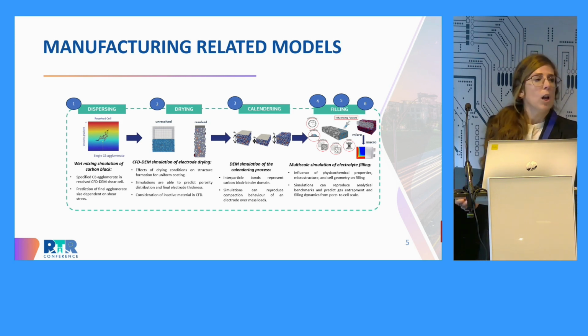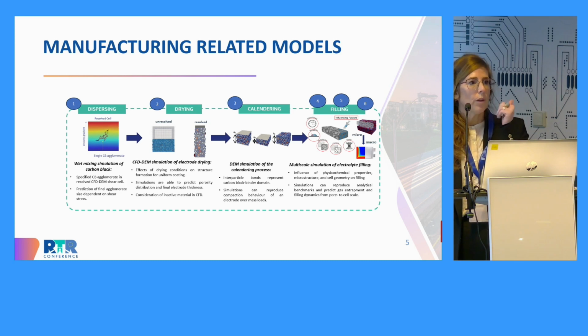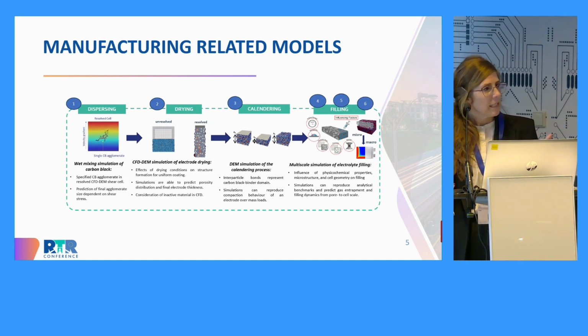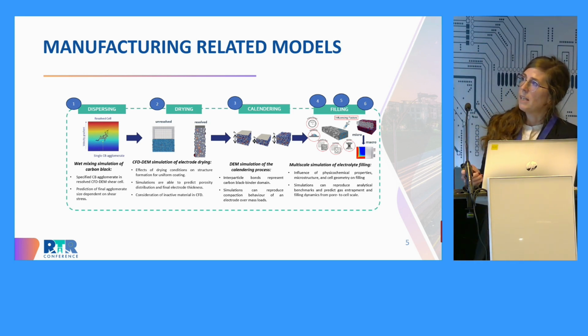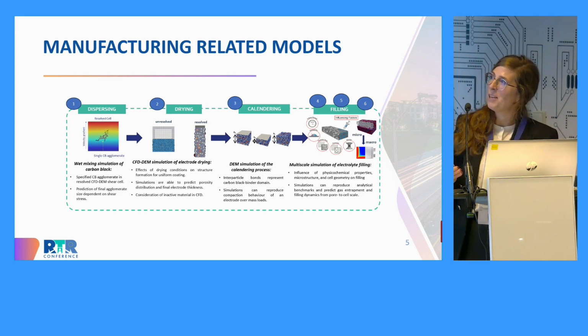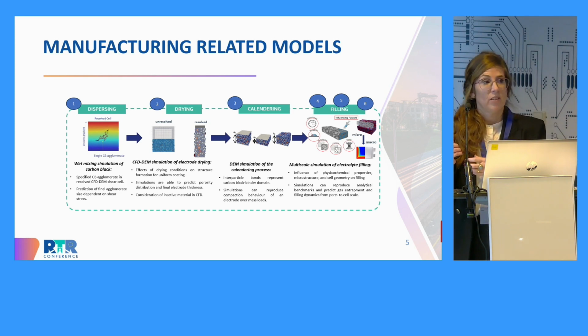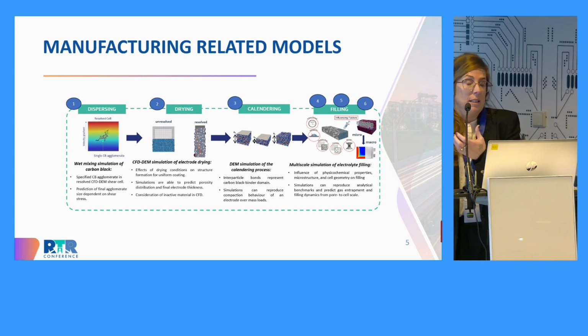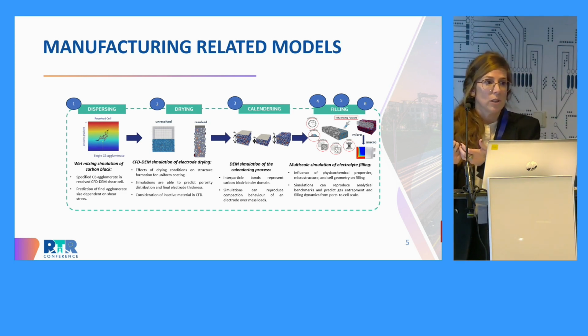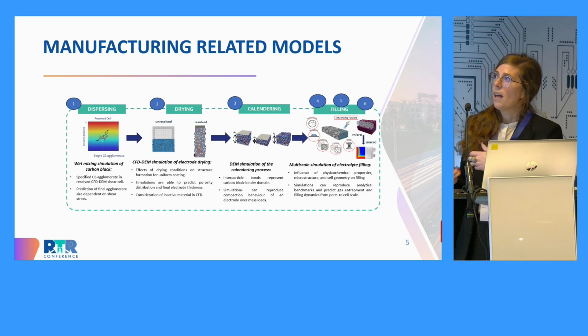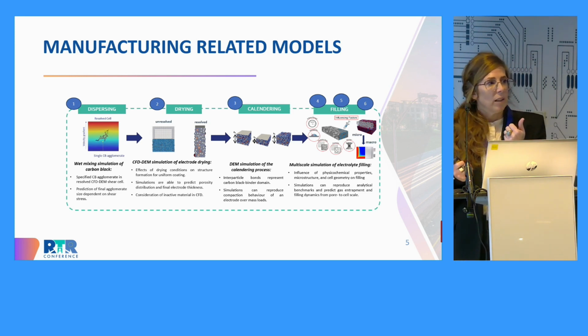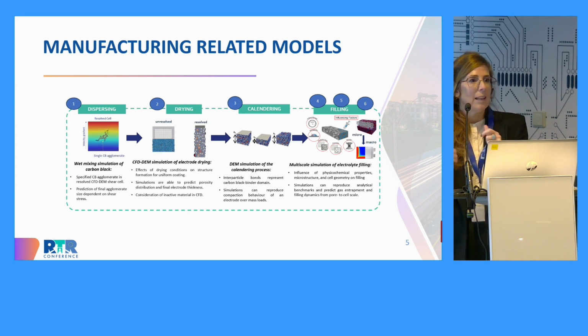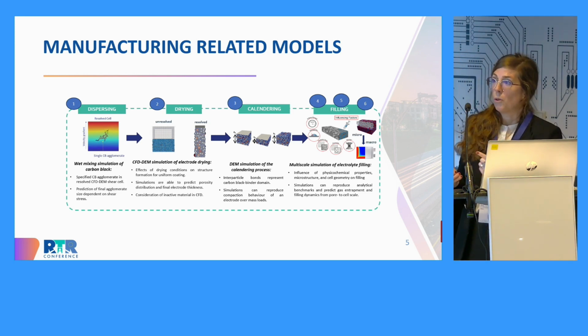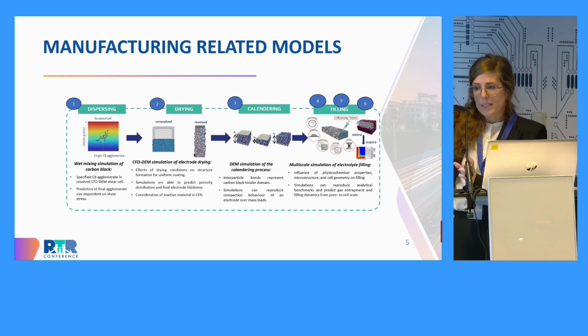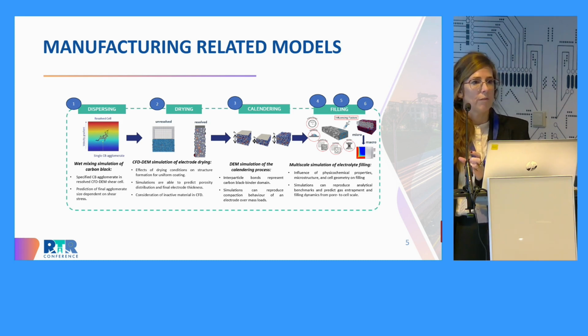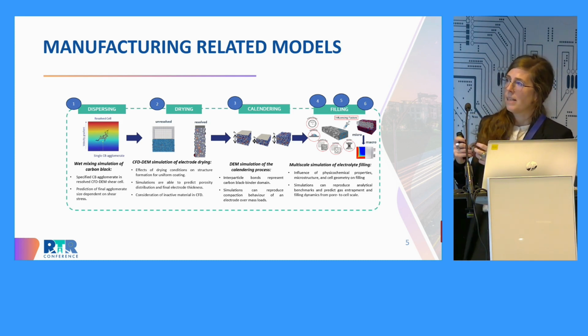then on the filling scale, we were tackling this step from a multi-scale approach. So they developed a lattice-Boltzmann scheme, also pore network modeling, and then also Richards equations, basically because we want to understand properly how to avoid gas entrapment in the cell itself, because this gas entrapment, for instance, can reduce the lifetime. So you need to know in advance which are the best parameters of the filling, taking into account that the nanopores of the binders will be crucial to address this issue, or the pores all along the active material, or the way or in which flow you inject the electrolyte will have a lot of impact again on these specific cell performance properties.